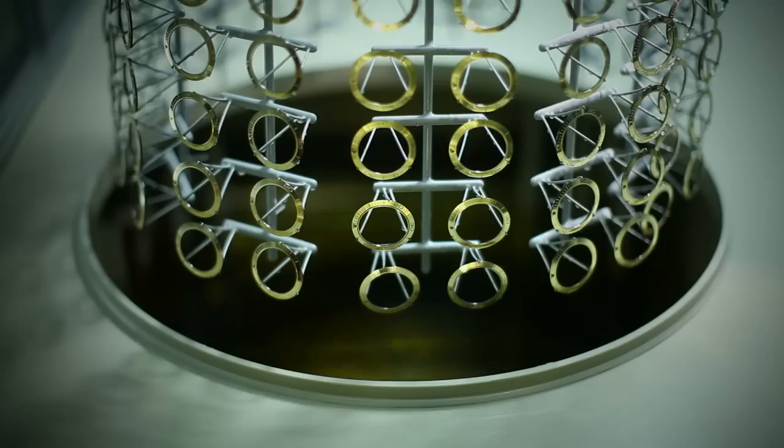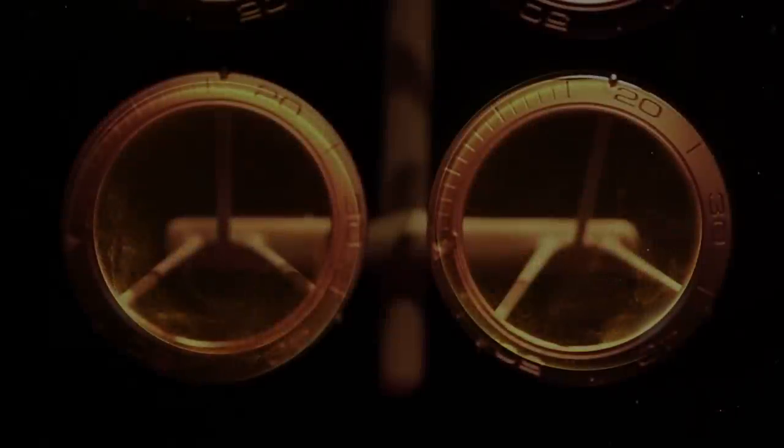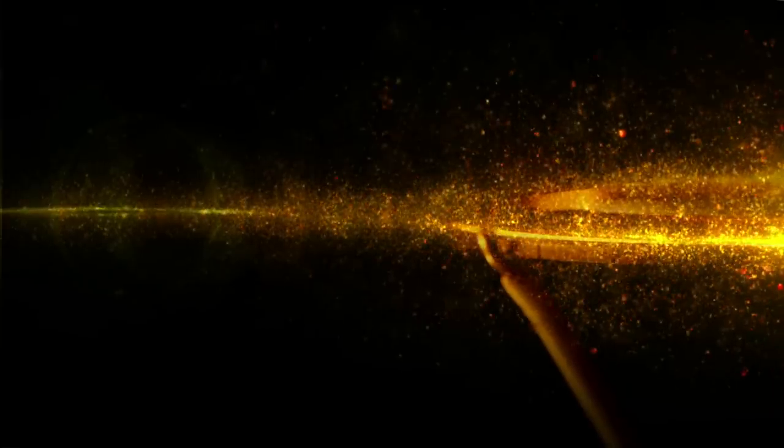The now-conductive ceramic rings are placed on a rack and submerged in a gold electrolytic bath for 48 hours. A thick layer of 18-karat red gold is formed that coats the ring's top surface.